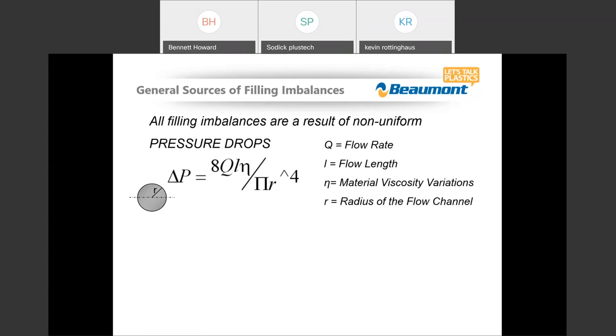So when we look at what is a result of non-uniform pressure, we can look at a simple change in pressure formula. Delta P equals 8 times our flow rate, Q, times L, our flow length, times eta, our material viscosity variation, divided by pi times the radius of our flow channel to the power of 4. It's easy to identify the variables because we can very easily cross out constants. So 8 obviously is a constant. Q is a constant because that is our flow rate being controlled by the injection molding machine. Assuming that your machine is operating fairly well and can maintain a consistent injection velocity from shot to shot, our flow rate is the same every single time. Next constant would be pi, and then the last would be 4.